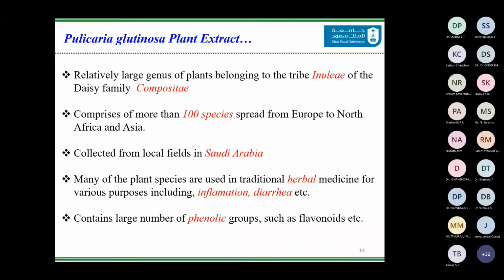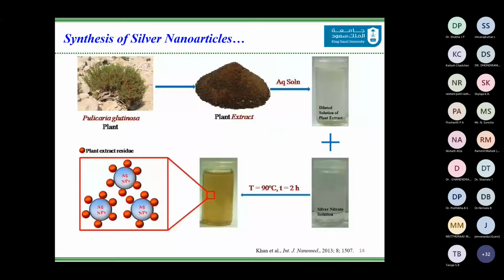We took the plant itself, the entire shrub, as you can see. We dried it and we powdered it. Once we powdered it, we dissolved it in water, and to this we added the silver salt. And within 2 hours of reaction time, at 90 degrees centigrade temperature, we were able to obtain amazing silver nanoparticles.